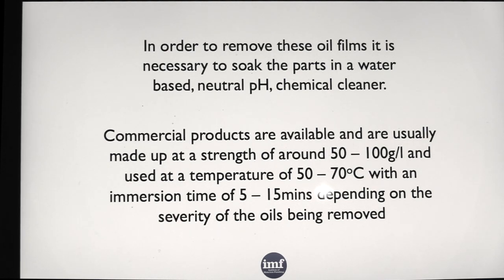Lots of surfactants in it, wetting agents, lots of emulsifiers to get the oil to soak off the part. There are commercial products around, not going into any names, but these are normally just powders made up between 50 and 100 grams per litre, temperatures 50 to 70 degrees centigrade, and immersion times 5 to 15 minutes. It doesn't really matter, it depends on how heavy the grease is. If you look at steels, for example, steels in chemical cleaners use very high alkalinity solutions, and they also pass electricity through them to make them fizz. As they fizz, all the grease comes off. You tend not to do that with aluminium. It tends to be really a soak process, and if you want to cause some disturbance, they use ultrasonics to clean it.